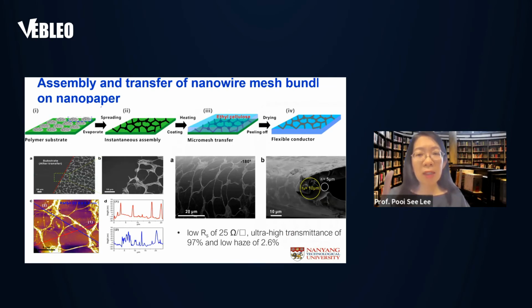In order to make the nanowire to be well distributed, we also employ the spray coating approach, where spreading of the nanowires onto the substrate, including nanopaper or polymer substrate, can be achieved. So this spray coating actually has the governing mechanism of spreading and evaporation method to lead to a bundle formation of nanowires that is formed onto the substrate.